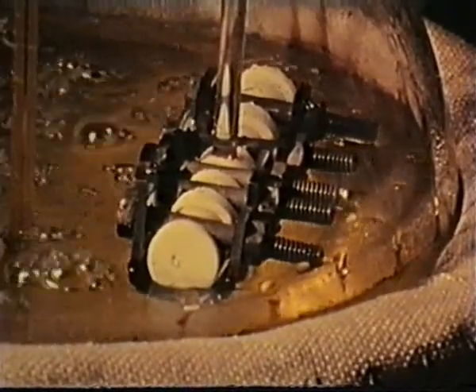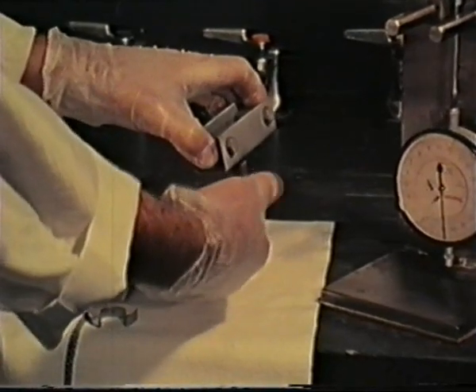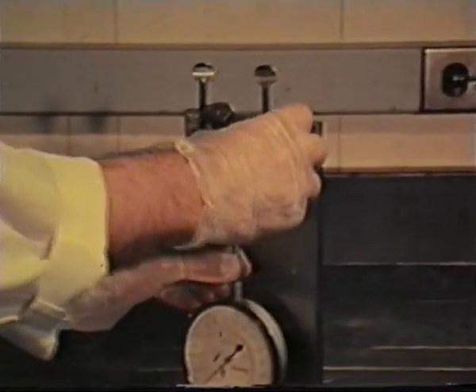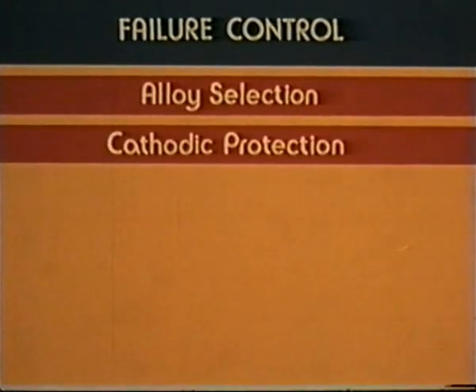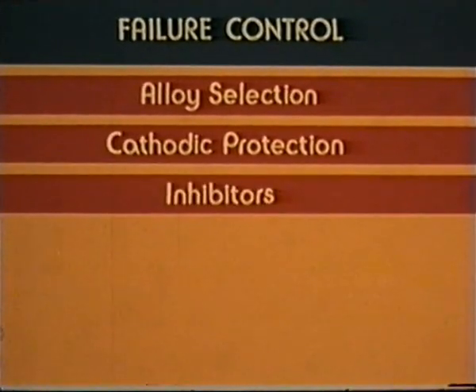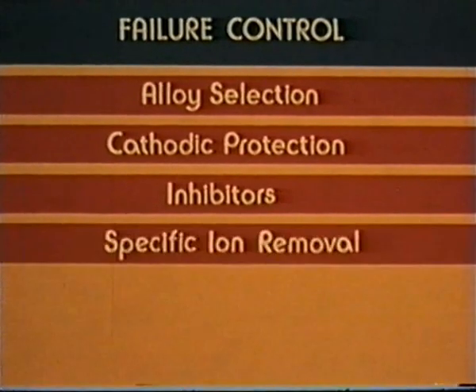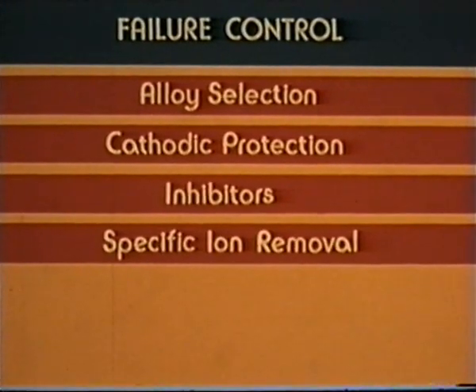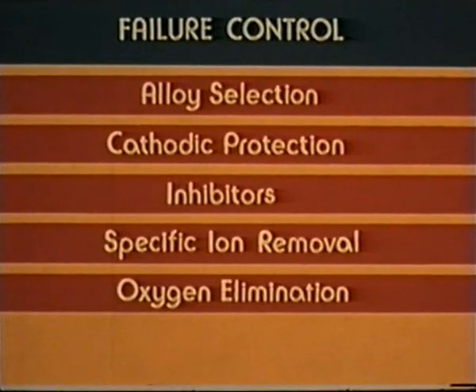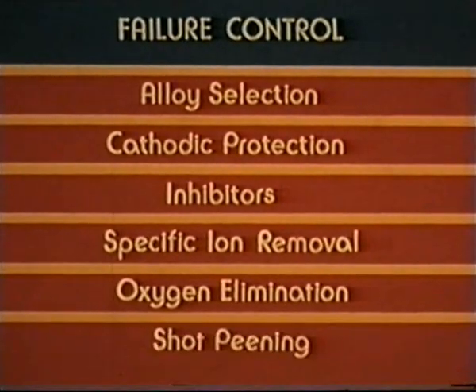Although a full theoretical explanation of stress corrosion cracking does not exist, a number of techniques can be used to reduce or eliminate failures. The most common practice is to substitute a resistant alloy not affected by the specific environment for the susceptible material. Other effective measures have been cathodic protection and the use of inhibitors. Sometimes the environment can be altered to remove the specific ion or control it at low levels. Limiting oxygen content has been effective. Shot peening has been used to introduce surface compressive stresses which offset residual and applied tensile stresses.